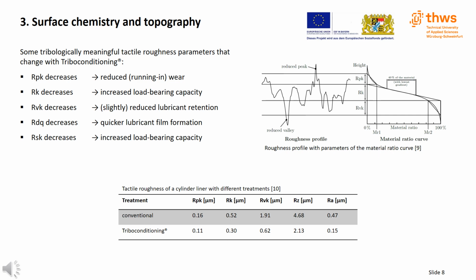Triboconditioning reduces all three of the mentioned parameters. The reduction of RPK reduces wear, especially during running in. A lower RK value increases the contact area and therefore increases the load-bearing capacity. Reducing RVK slightly reduces lubricant retention.